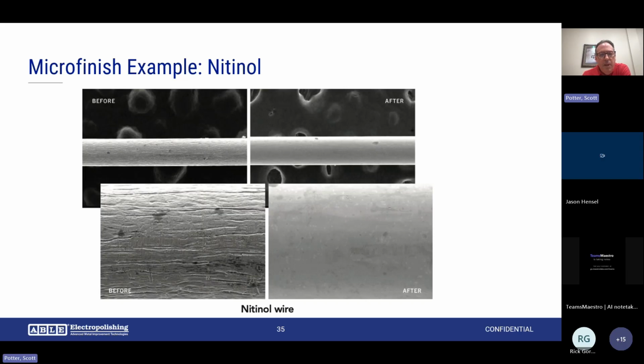But one of the things that makes it difficult to electropolish is that it's very good for standing up to the situation, as far as blood and so forth. It's also hard to break down with our electrolyte. So we actually have a specific electrolyte that we developed with Fermilab. We were working on some niobium parts for Fermilab, and we were able to develop something that worked well on refractory metals and inert metals. So it's becoming very widely used in the medical device field.